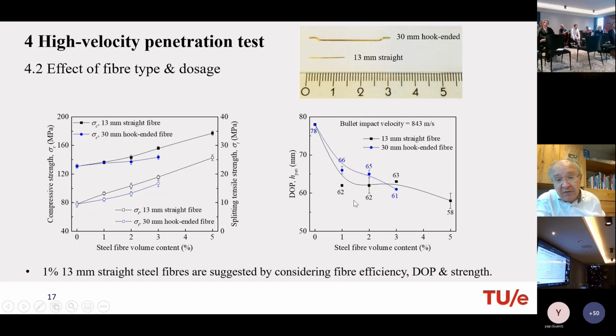And here you can see the effect of steel fiber volume on impact, how deep the bullet penetrates, the depth of penetration, DOP. And you can see that when there's no steel fibers, then it penetrates 80 millimeter or even more. But as soon as you add steel fibers, you can see already with 1%, then it is reduced to 60 millimeters. And you can also see that beyond 1, let's say 2 percent, further steel addition has not much use anymore. So I think we continued mostly with 1% steel, which is quite low actually for these purposes.